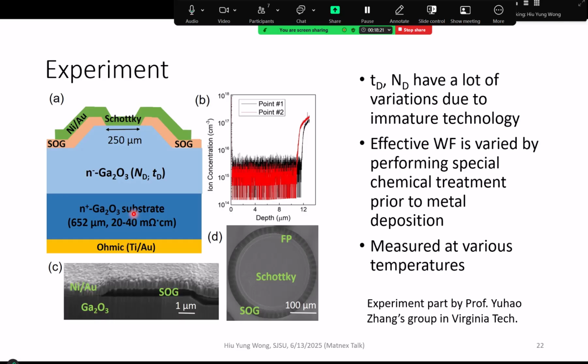Right? So it is a Schottky barrier diode. Basically, everything is N-type, and the bottom is the ohmic contact. The top is a Schottky contact with nickel gold. So this formed a diode. This was fabricated by our partner at Virginia Tech at that time. Because it was pretty novel, it's difficult to fabricate. You have doping variation in this drift region. You have thickness variation in this drift region. And at the same time, when fabricating the diode, they deliberately performed some chemical treatment before metal deposition. So you have a different effective work function also, due to the interfacial state.